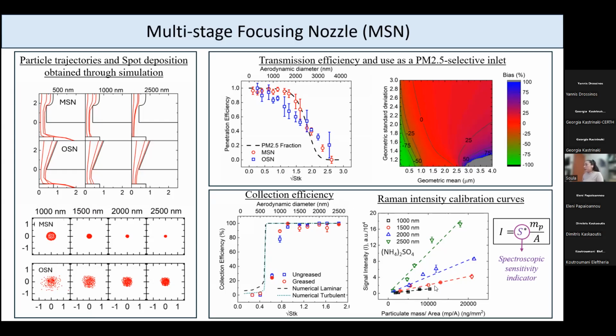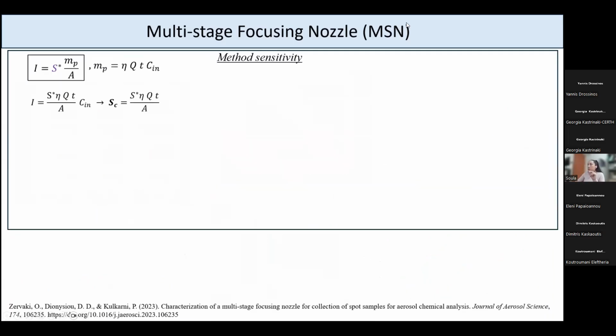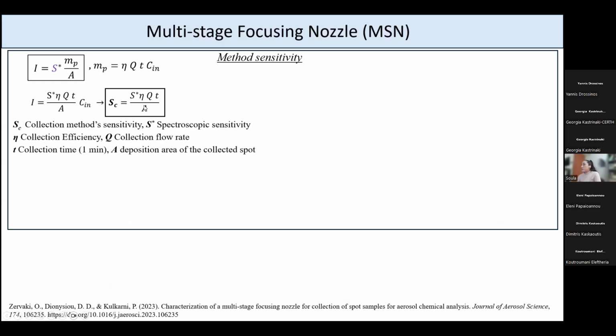And in every calibration curve, this is the equation that we get, with the slope denoting the spectroscopic sensitivity indicator, which is completely independent of the collection method used. It's only dependent on the analytical method that is being used. For that reason, we can take this equation, and by replacing the mass with this term, we can obtain a new equation, which is the intensity as a function of the aerosol concentration, where the slope is denoted by SC, which is the collection method sensitivity.